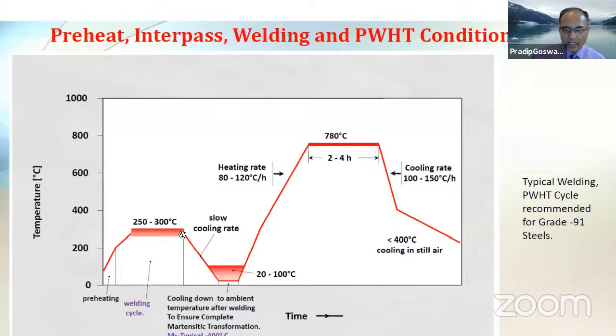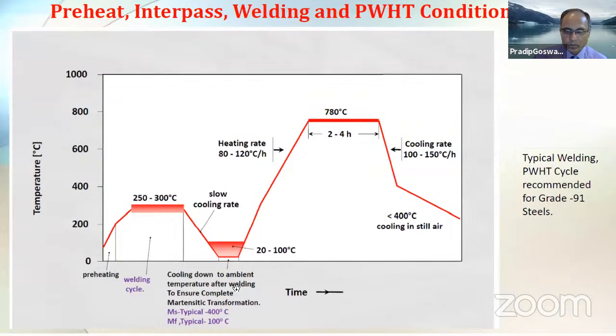Once the welding is complete, from this point onward, the alloy has to be cooled down, and this has to be a slow cooling cycle. This is 100 degrees centigrade, where, as you see here, is the MF, or martensite finish temperature. So 100 degrees centigrade or below. It says here that cooling down to the ambient temperature after welding ensures complete martensitic transformation. Typical MS, martensite start temperature, is 400 degrees centigrade, and MF, martensite finish temperature, is 100 degrees centigrade.